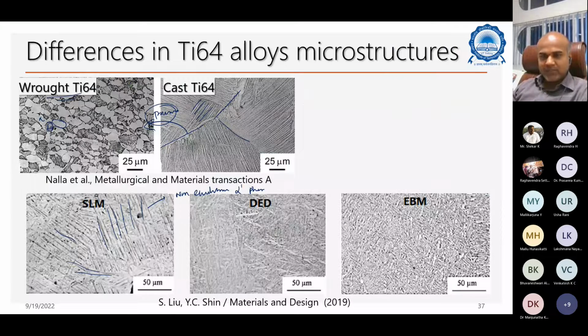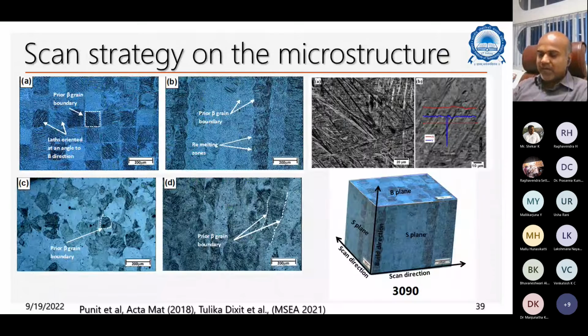Okay, this is a microstructure made by SLM, using a traditional one-line scanning. Okay, zigzag scanning. But if you do island scanning, you see a completely different microstructure. Okay, this we don't call a microstructure, I mean, it is a microstructure, but to differentiate this from that, we call it a mesostructure here. What you can do is create small blocks here. Each block exhibits a different orientation, different grains. Okay, so this is what we have varied, 90 degrees scan rotation, as we were talking about before.